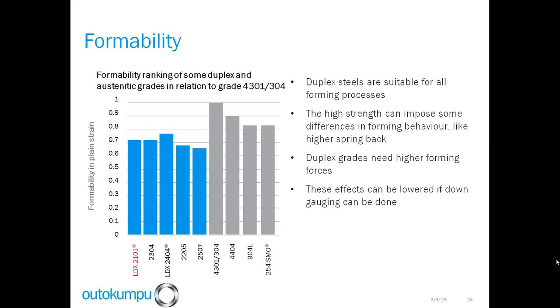When we look at formability in general, this is mainly draw formability. We can see that the forming characteristics are going to be somewhat less for duplex when we compare them to austenitic materials. We also have higher spring back, again, as we mentioned, with the higher strength materials. If we can take advantage of down gauging, going to thinner materials, these effects can be minimized.